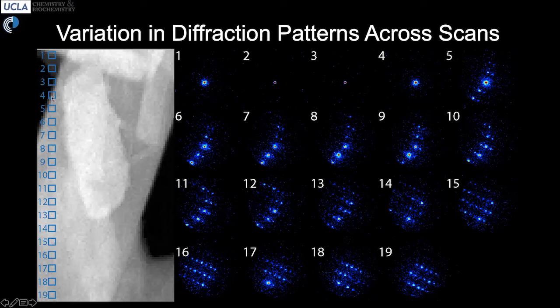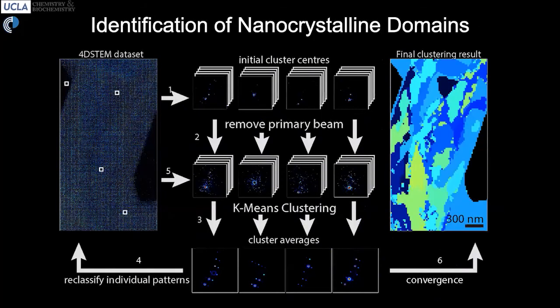If it impinges on a piece of the crystal, it immediately starts diffracting. And so you can see these higher order spots that appear as a result of the beam interacting with the lattice present in this region of the specimen. As you go farther and farther into the core of the crystal, you can see that that diffraction is changing. And we were trying to really not only parse out the differences in diffraction across these two-dimensional spatial maps of the beam raster scanning across the crystal, but also try to understand what the underlying physical basis might be for this behavior. And so we've developed algorithms to parse out those diffraction patterns.